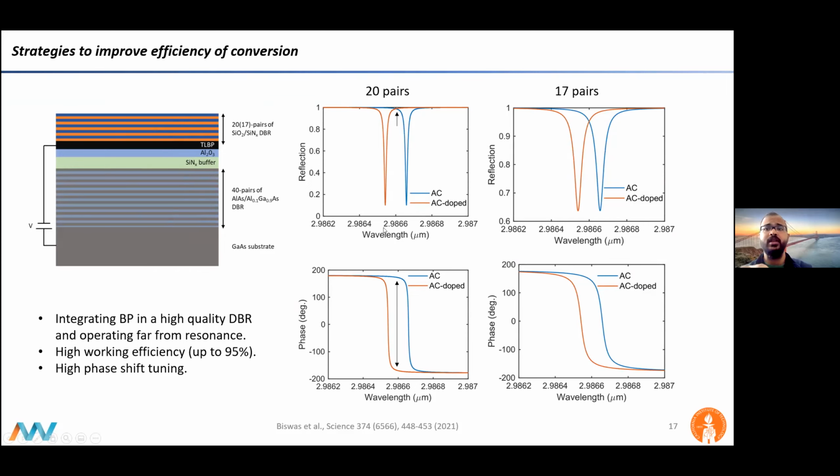And over here we see that we can have very high reflectivity at the inflection point of around 95 or 98%, and we can have a 2π phase shift, which is quite exciting for getting a large polarization inversion between the doped and undoped case for the armchair direction.